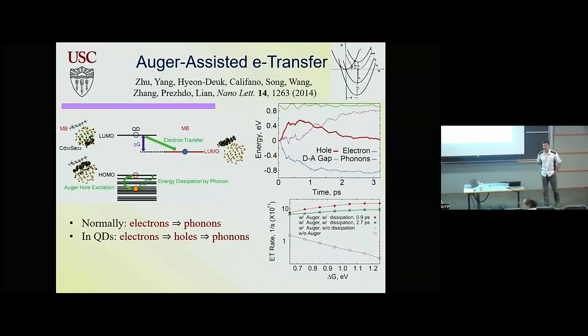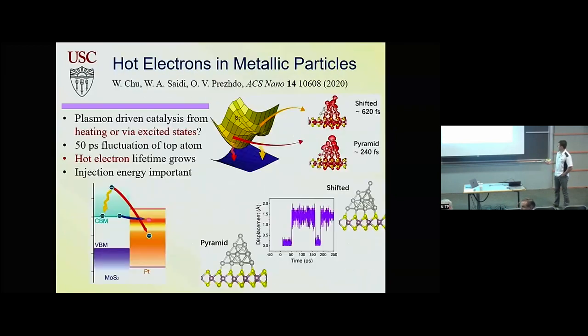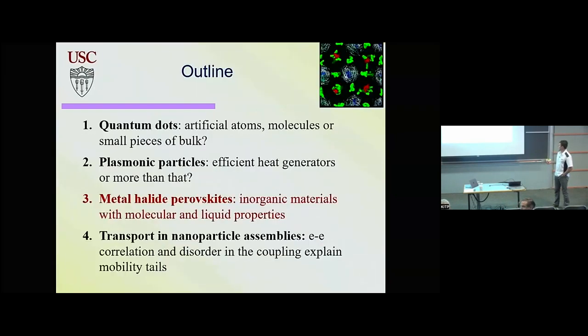So you mentioned perovskite also, the polarons or the charge solvation. And I can imagine this in bulk, but can you comment on what happens with polarons when you go to nanocrystals? Right, so I think polarons are very large. I think they're maybe even larger than excitons. So probably when you have a crystal where you see a confinement effect in terms of spectroscopy, you're already confining your polarons as well. So you still have polarons, but there's less screening because you have a smaller polaron. So I think it still should exist.